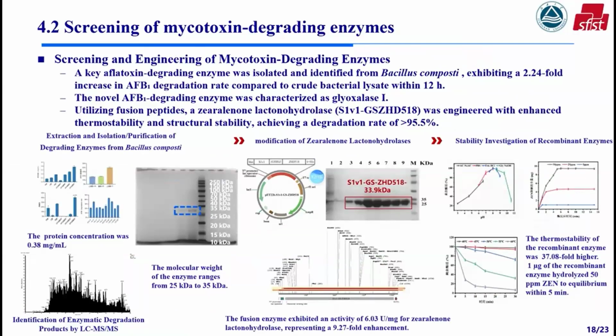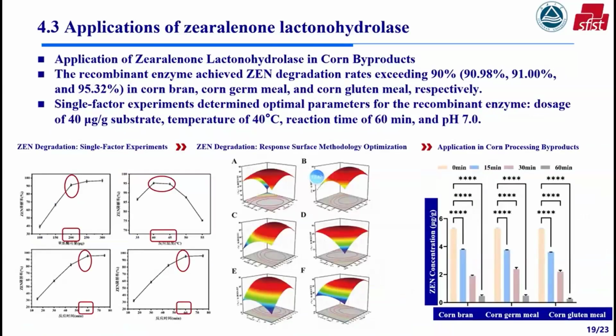However, in particular applications, the enzyme's thermal stability or activity may be insufficient. Thus, we perform rational modification of these screened enzymes. For example, fusion with a short peptide sequence enhances the thermal stability of the ZEN hydrolase. Subsequently, the modified ZEN hydrolase was applied to various corn byproducts after optimization of degradation conditions. A degradation rate of ZN reached over 90% in just 1 hour for all tested materials.